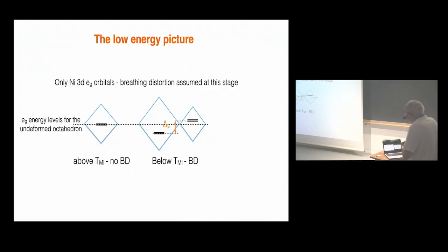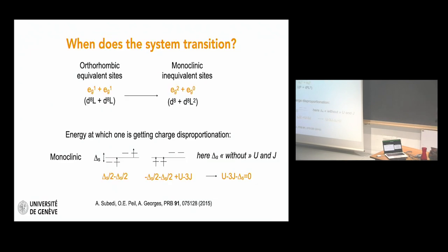Now, in this low energy picture, where we consider only the nickel eg orbitals, you see that the gain in energy here is what we call delta S. And we can calculate the energy at which there will be this transition, and this is done in this paper of Alaska Subedi, Oleg Peil, and Antoine Georges. What they're doing is comparing the situation at high temperature, orthorhombic with equivalent sites, to the monoclinic phase with inequivalent sites. And you see here the situation in the monoclinic phase.